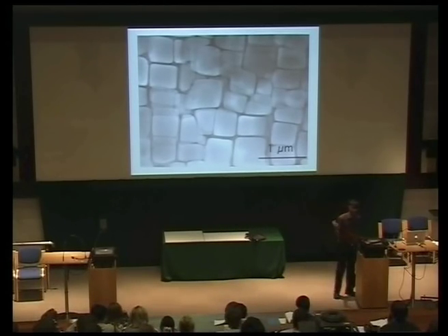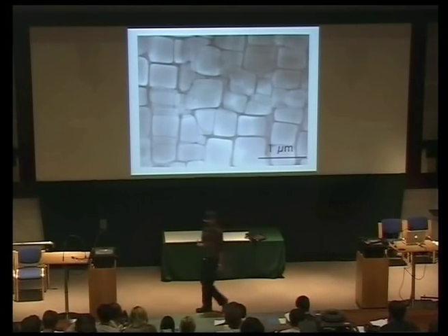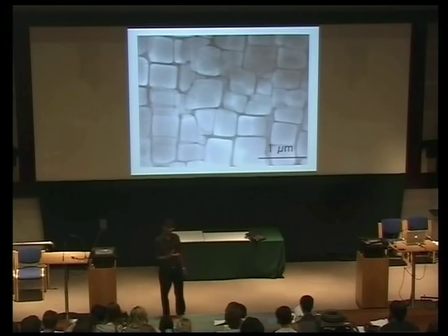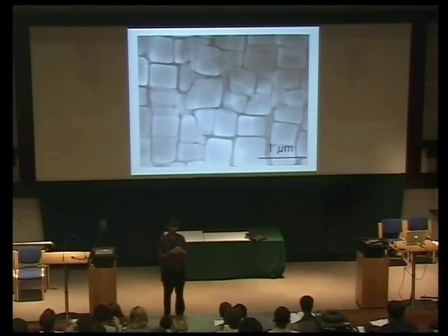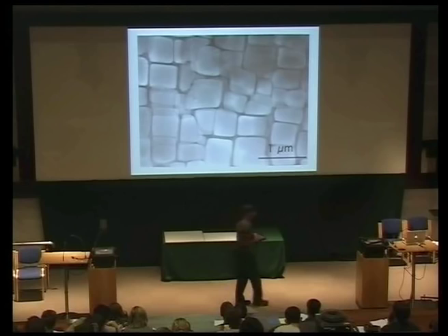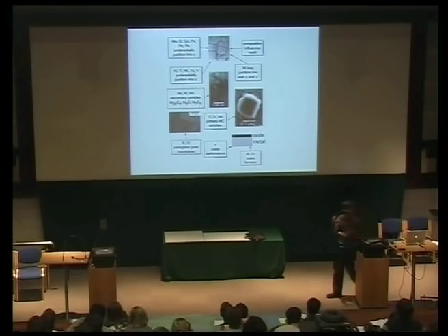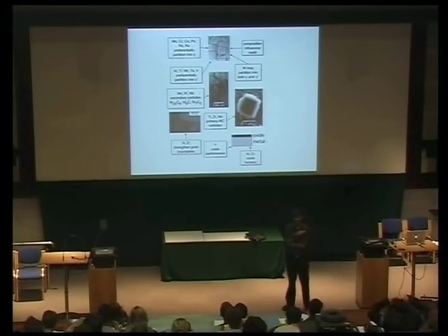Now, this gamma prime itself is interesting, and a very large amount of research was done about 10 years ago on seeing whether we can make high-temperature materials out of pure gamma prime. That means just the ordered phase. Supposing we eliminate the matrix altogether and we just look at Ni3Al or Ni3AlTi. And the reason for looking at that particular intermetallic compound is that the strength of that actually increases with temperature.